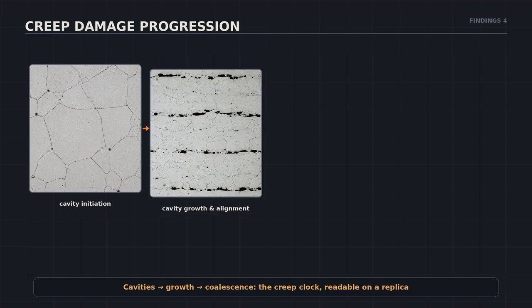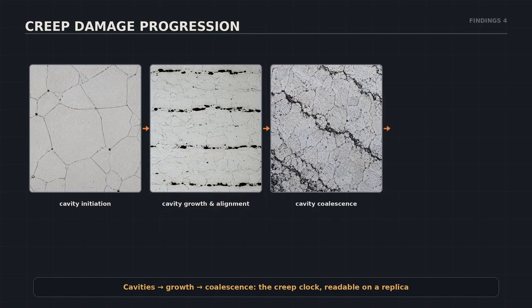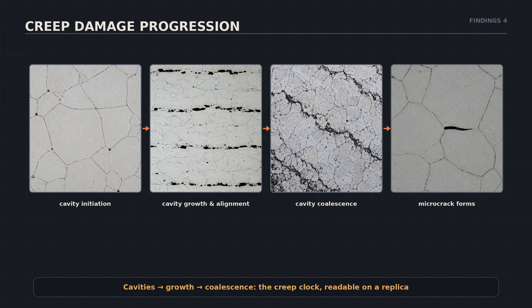Now the big one for high-temperature plant, creep. It starts invisibly, isolated cavities nucleating on the grain boundaries. Then the cavities grow, fed by stress and temperature. They multiply and start to link up, coalescence, aligned perpendicular to the stress direction. And the final step, the chains become microcracks. This entire sequence is readable on a replica, no other field technique sees it.